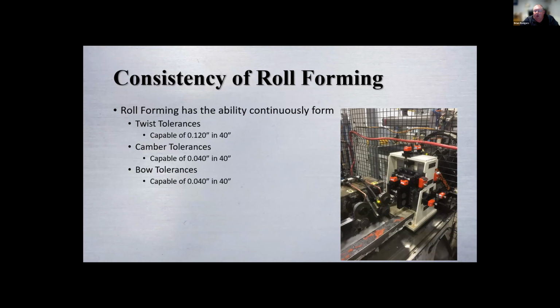Here's a picture of an appliance part. It's actually going through a roller straightener, and it's a dual head, so there's a set of rolls on both sides. And this one here is able to hold a very consistent part. I do believe we're holding 10 thousandths of an inch in 40 inches on this, but it's going into an automatic bender, so it has to be very consistent so the robot can pick the part up, carry it over, and put it in the bending operation for the final product.